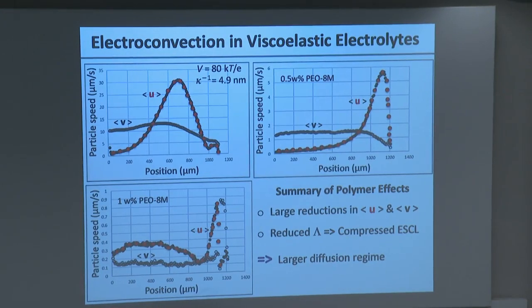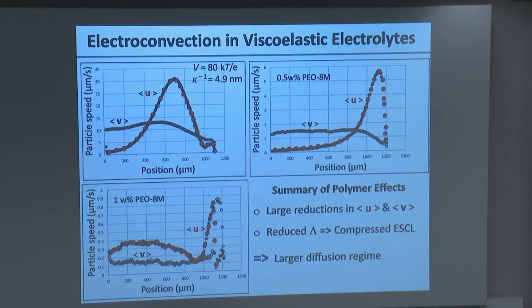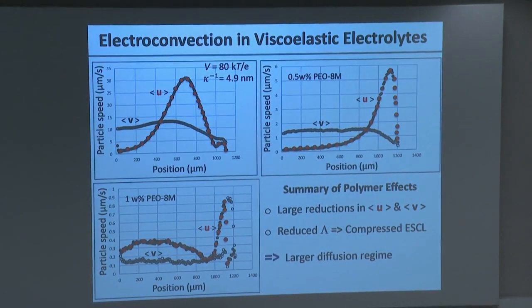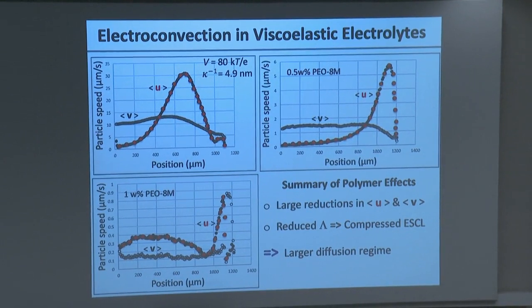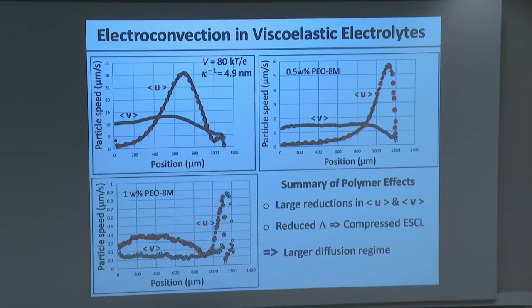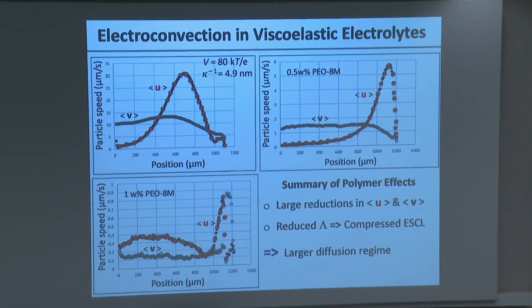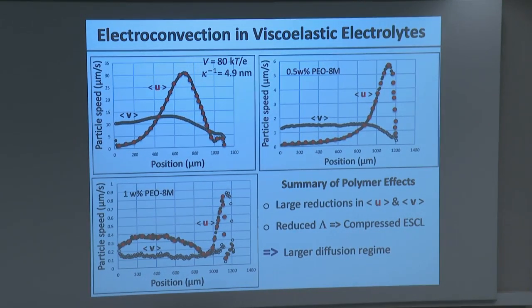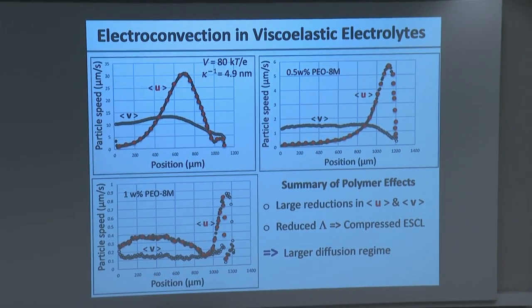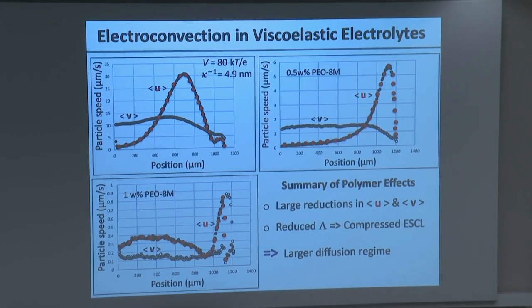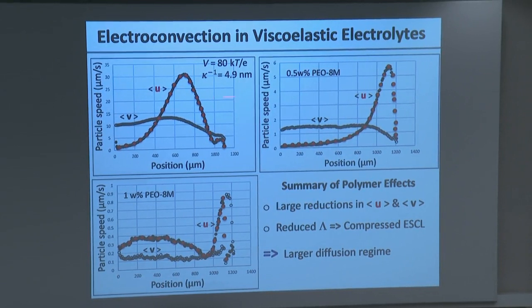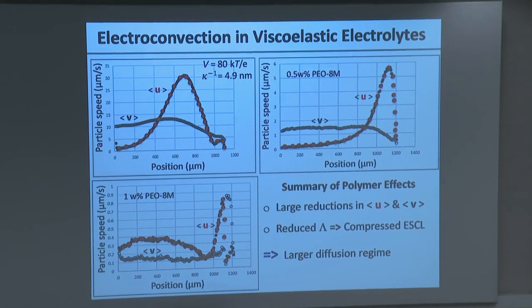So next, I did it. Okay, and this is a bit abbreviated, so I did it. I just put the polymers in, and I chose polymers that had relatively high molecular weights. So these are 8 million PEO, and polymers that had relatively low concentrations to make big pores like I wanted. So 0.5 weight percent, 1 weight percent. And I used that device that I showed you earlier to basically monitor how the velocity of fluid was going on near the wall. And what you can see is that as I change the concentration of polymer, the shape of this structure doesn't change a lot, but the values change a lot, right?